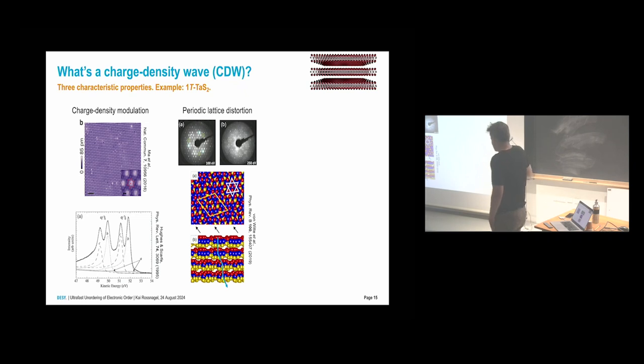The second thing is, of course, the periodic lattice distortion, and this is typically studied in reciprocal space using diffraction techniques. Here, LEED, low energy electron diffraction, and in this example, tantalum disulfide, this can be very complicated. It can have this Star of David-like periodic lattice distortion, but it can also have this stacking of different charge density layers in the third dimension. So this can be very complicated patterns in real materials.